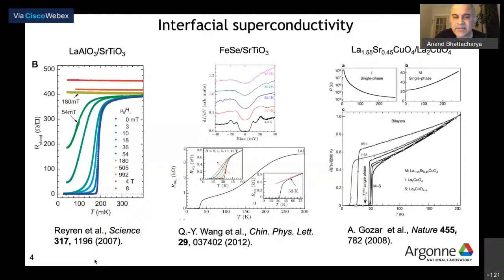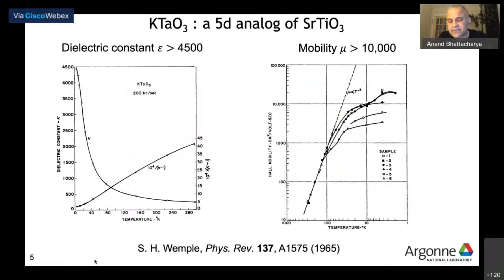Okay. So potassium tantalate for this audience might already be known. It's a close cousin of strontium titanate, right? It's a doped 5D insulator. And so there's a band gap of like 3.6 eV, I think. And then it has a dielectric constant that does something very similar to what strontium titanate does. As you cool it down, the dielectric constant rises pretty steeply to a value of about 4,500, as you can see on the left.